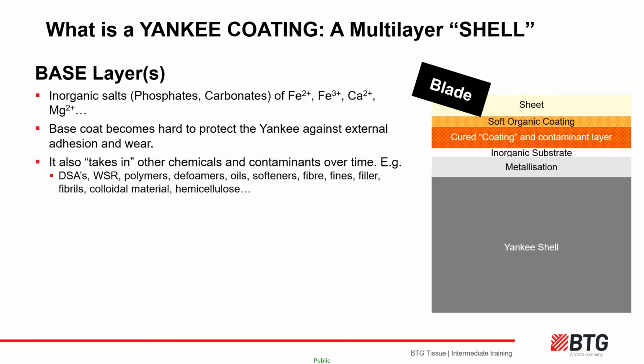On top of this, we would see the cured coating layer, which protects the Yankee from corrosive and erosive wear and restricts the metal blade to metal Yankee contact and subsequent adhesive wear. This is made up of cured base coating, not initially removed by the 3 doctor blades, which has also attracted papermaking components and contaminants and baked on the surface of the Yankee to form a very hard protective layer between the Yankee substrate and the more recently applied coatings.